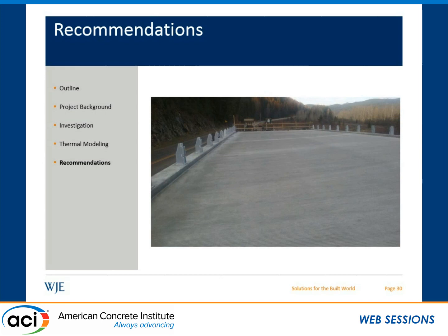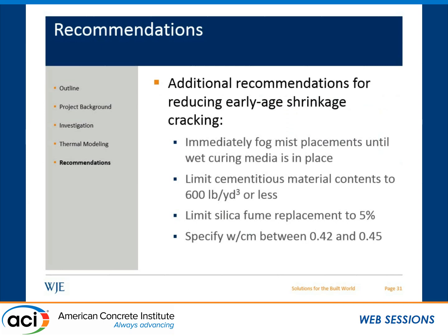He saw a few hairline cracks, and that was it. We also made a few other recommendations to limit some early age shrinkage cracking. We had talked about before, we saw some evidence of plastic shrinkage, and there was one bridge that had some evidence of autogenous shrinkage as well. So our recommendations to reduce some of the early age shrinkage cracking were to immediately fog mist the concrete until wet curing media was able to be placed.